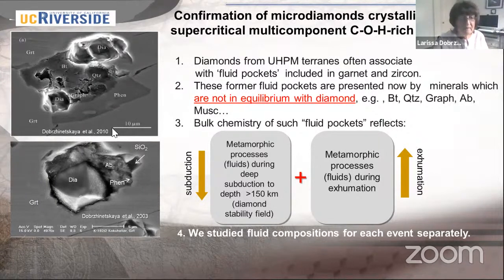For example, here you see a 10 micron bar scale. So this inclusion in garnet, okay, it contains many minerals, and the size of this inclusion is 20 to 30 microns. What we see here, we have one diamond crystal, another diamond crystal. We see biotite, we see quartz, we see graphite, and we see phengite. So we have this isolated pocket, 1, 2, 3, 4, 5 minerals together. So we believe that they were crystallized from melt or from fluid.